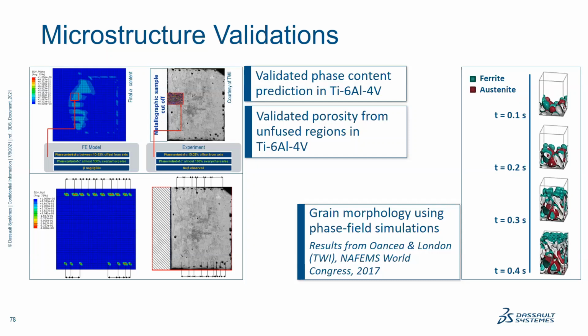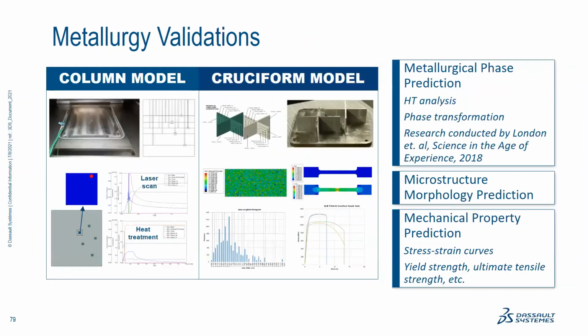So these simulations give a lot of insights. So you can plot contour variables, like, say, the alpha fraction of the phase, or you can even look at the kind of residual life also for different locations and so on. Other metallurgical validations are shown here. So you can take localized solutions. So you can also take into account parts which are printed in cruciform form, like, say, then machined out, and then you can test the tensile specimens to understand the macro level behavior of these materials. So instead of going for localized properties, you can also test from uniaxial test specimens which are printed, machined out, and then tested, and use those kinds of data for mapping the constitutive equations.